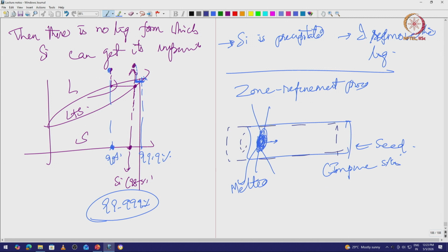So, this region which was melted now has solidified, but after it solidified, I am also slowly removing the liquid. It is no longer in contact with the liquid, because the liquid region is somewhere else. I have moved this away from the place where it should melt. So, by just thermal gradients, I am going to create a temperature profile where I have physically separated out the liquid region from the solid region.